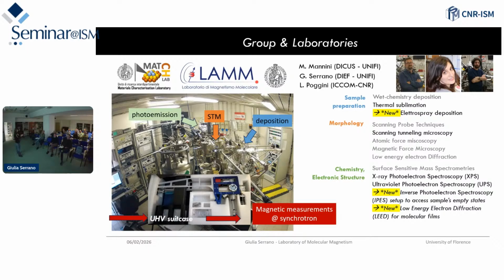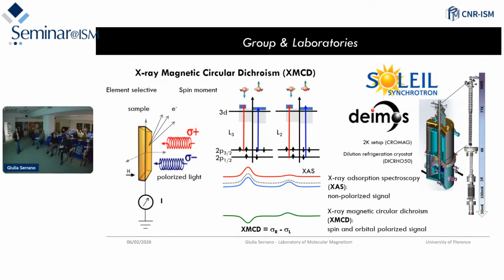The most important work is carried out at the synchrotron, because we need a magnetic characterization for our molecules, and this is done by, of course, preparing our sample in our setup in Florence and shipping it through a UHV suitcase directly to the XMCD facility, DEIMOS, at the SOLEIL synchrotron.